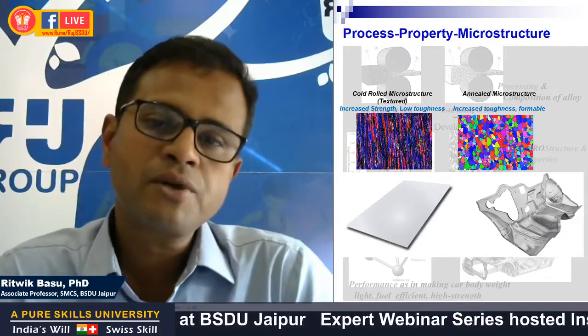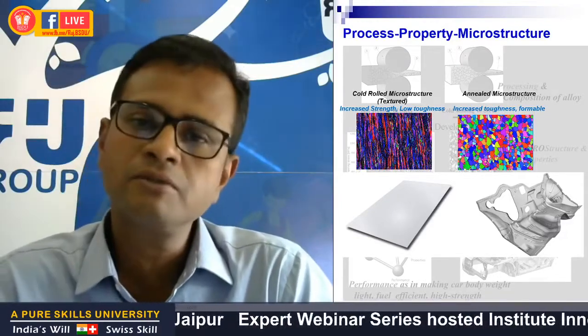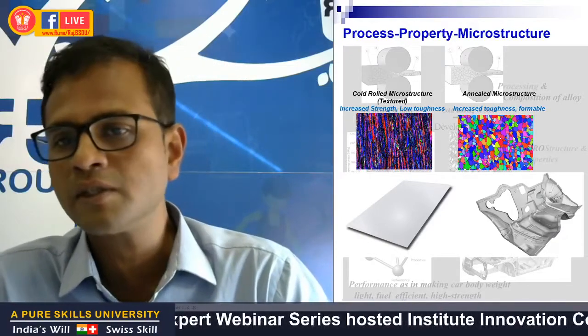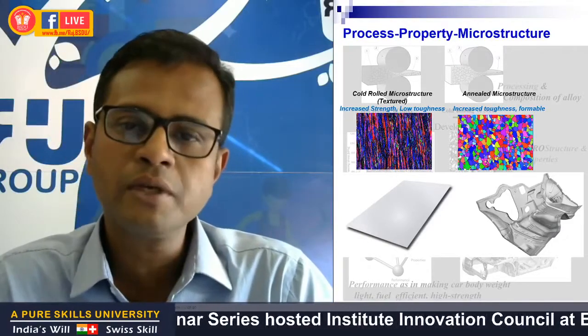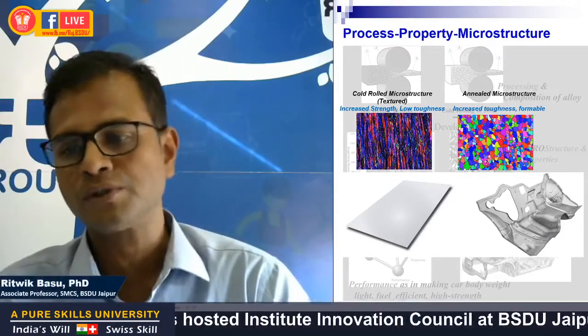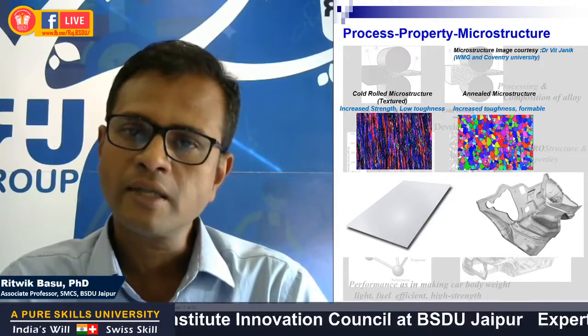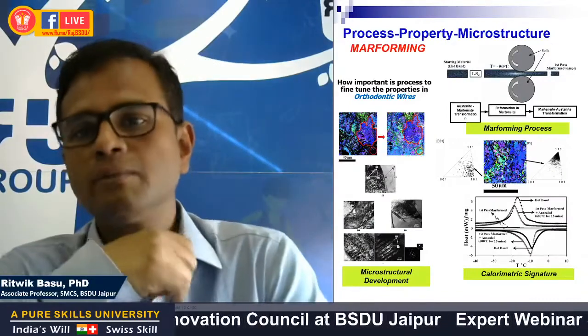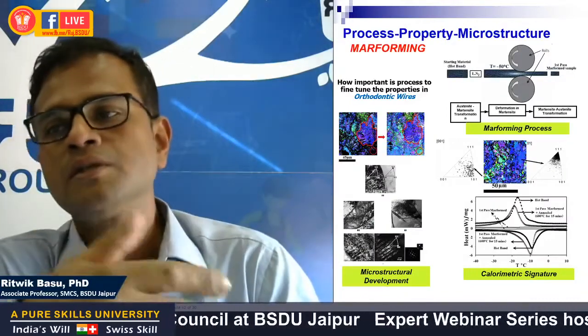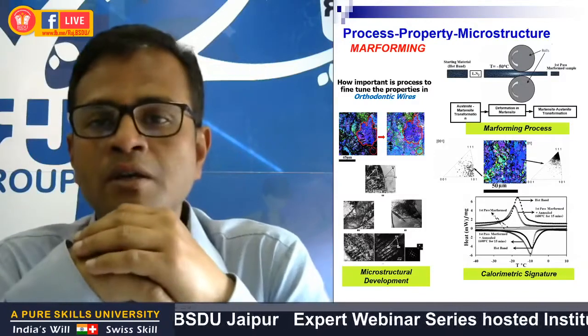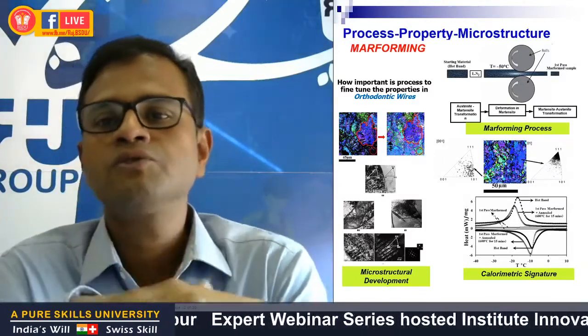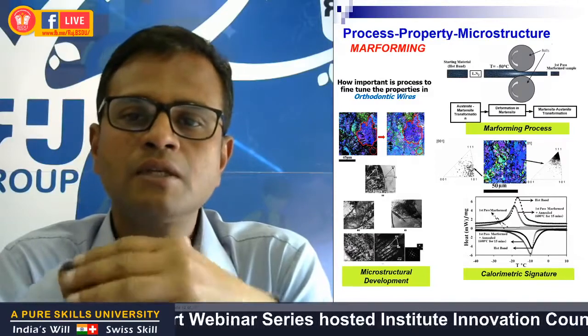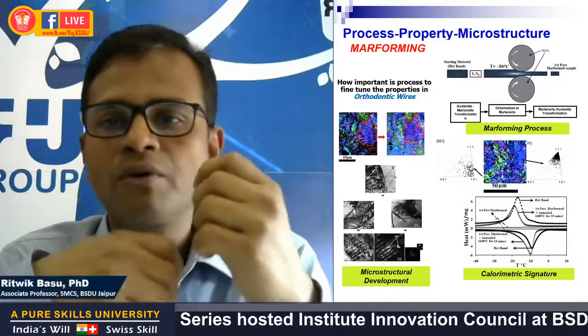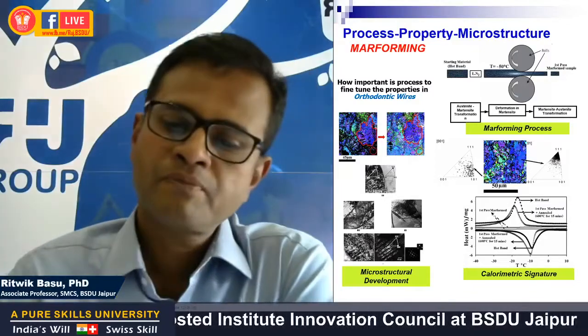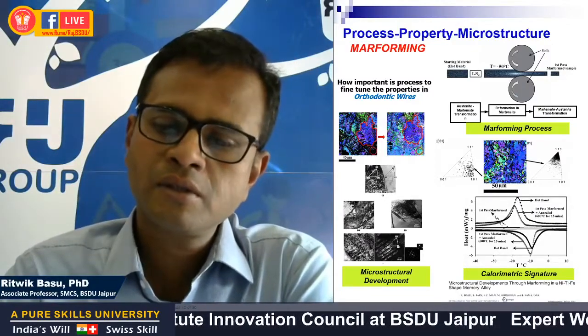So the beauty of heat treatment is therefore to impart the material with the right combination of strength and toughness. And the way we do it is through fine-tuning the microstructures. And that annealing can alter the microstructure significantly could also be understood through this following example. So this is an example taken from one of my earlier research works on nickel titanium shape memory arch wires used for orthodontic applications.